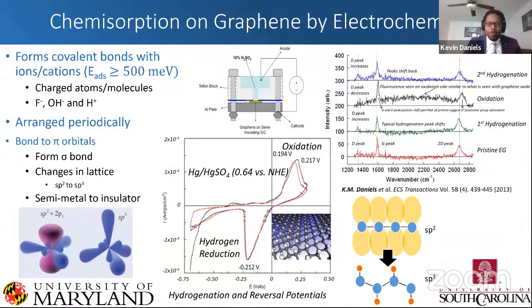And this is going off of work from when I was a graduate student at University of South Carolina, where I was trying to put hydrogen on graphene to try to change it from being a semi-metal to an insulator. And so this involves not the physisorption of molecules, but the chemisorption. These are much stronger bonds, in excess of 500 millielectron volts. And typically you would want these charged atoms or molecules, so these ions and cations are what you need in order to bond to graphene. And it's already pretty difficult.